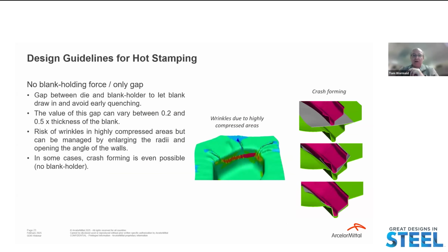Blank holders that are commonly used to control material flow in cold stamping are likely to cause issues in hot stamping by promoting early quenching on the binder surface. A gap is usually utilized instead to allow the flow of material into the die. The gap value is commonly 0.2 to 0.5 of the blank thickness and can be adjusted as needed. Using gap control can make stampings more prone to wrinkling, but there are geometry adjustments that can be made, including changes to the radii and wall angle. For some selected part geometries, crash forming with no blank holder whatsoever is even used in the hot stamping process.